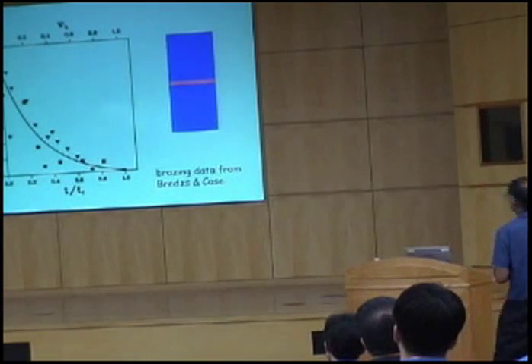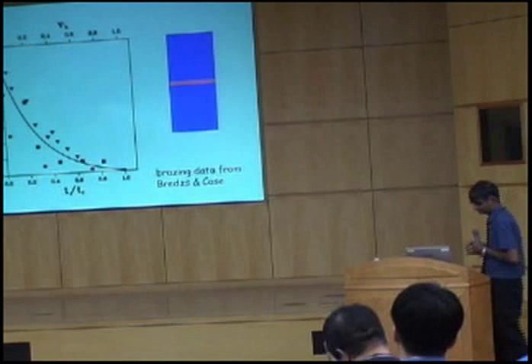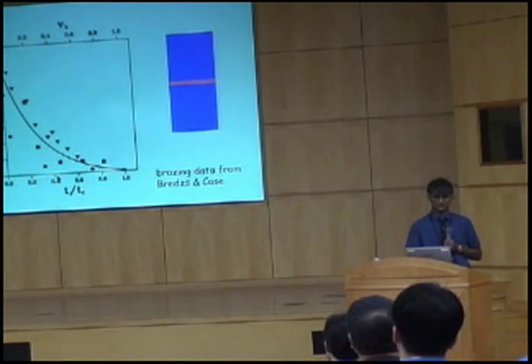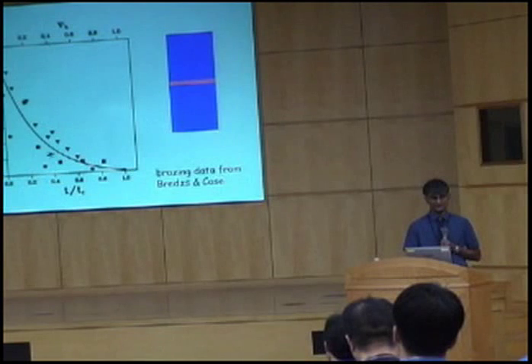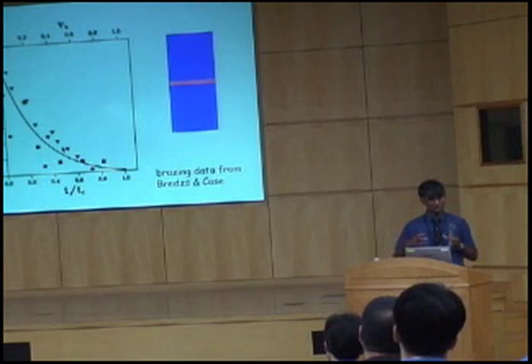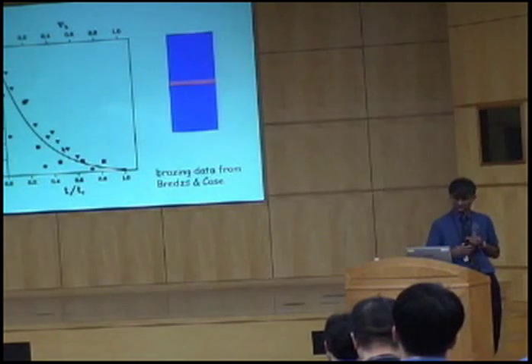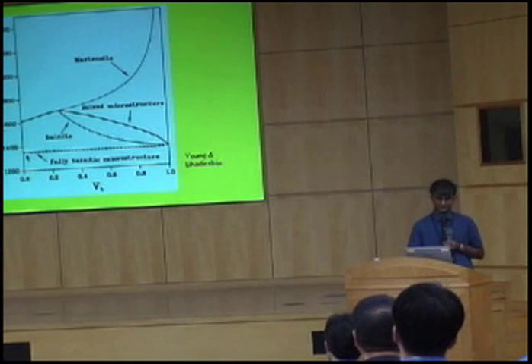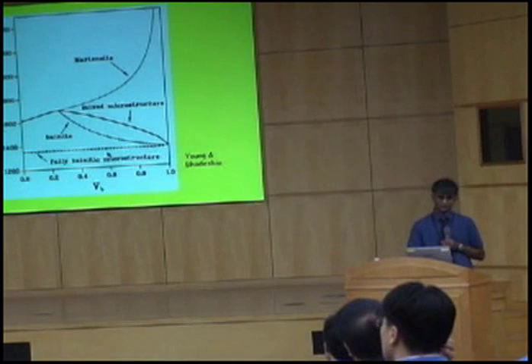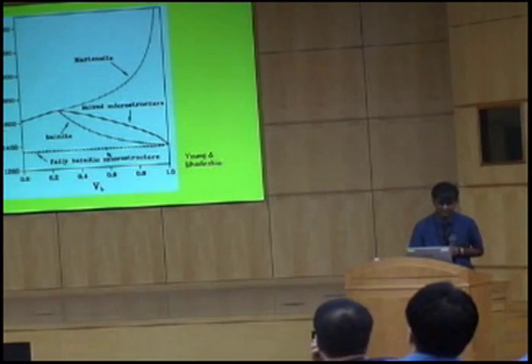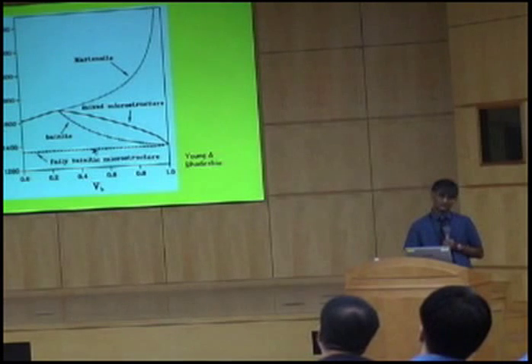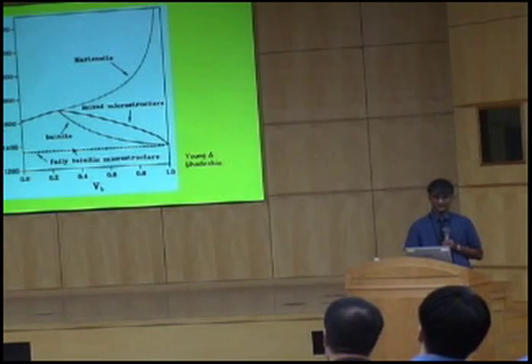We can use this curve to actually model bainite. We can say that, look, if my volume fraction is 0.4 of bainite, then the actual strength of bainite will be higher than if it was 100% bainite because of the constraint provided by martensite. Okay? And when we do that, if this is the strength of a 100% bainitic structure, first of all, we will increase the total strength of the microstructure because we are partitioning carbon into the material. So the strength of bainite will be higher than that of 100% bainite.